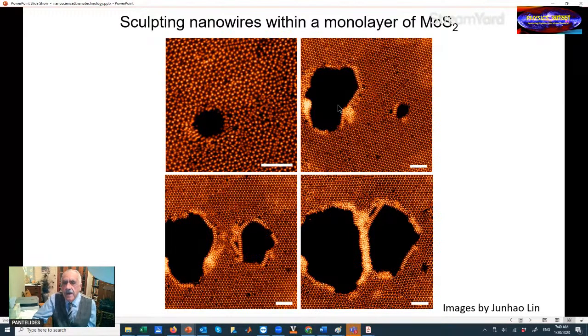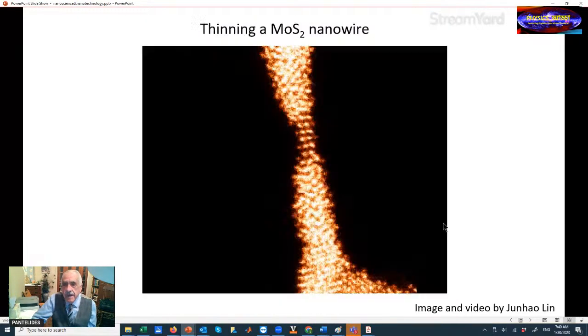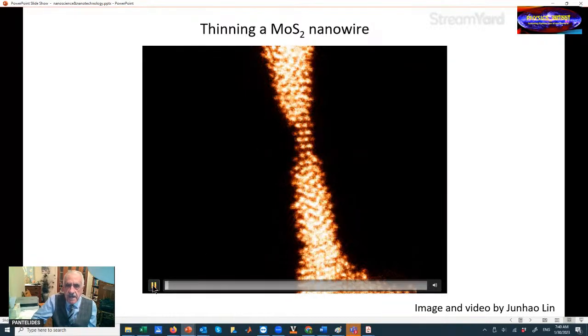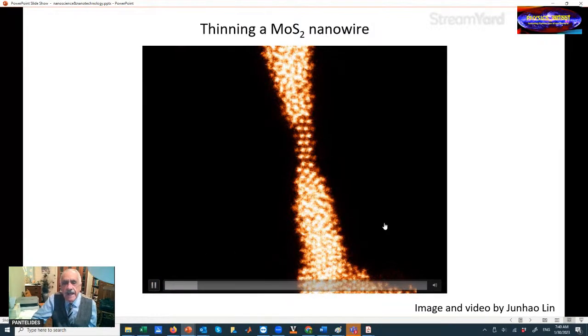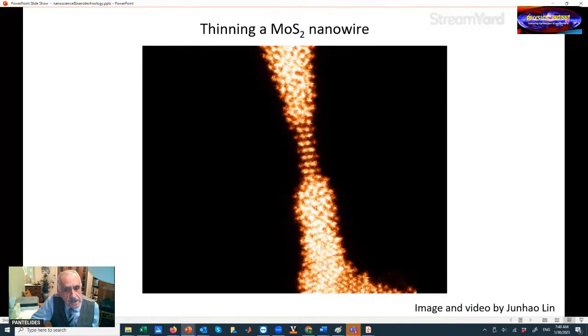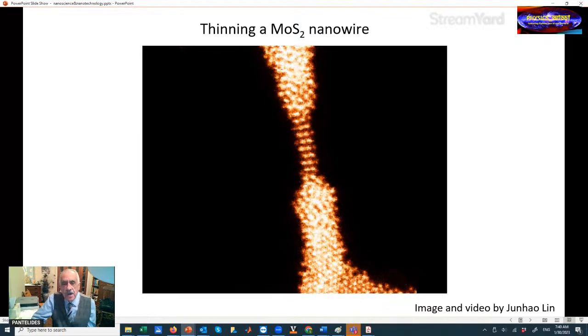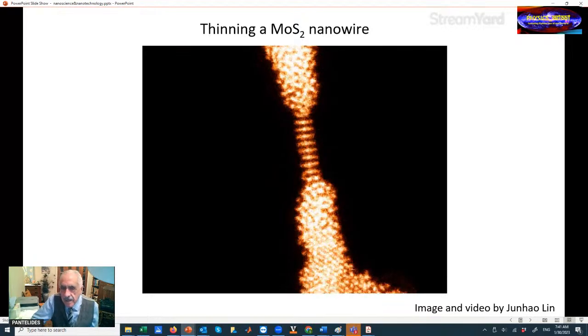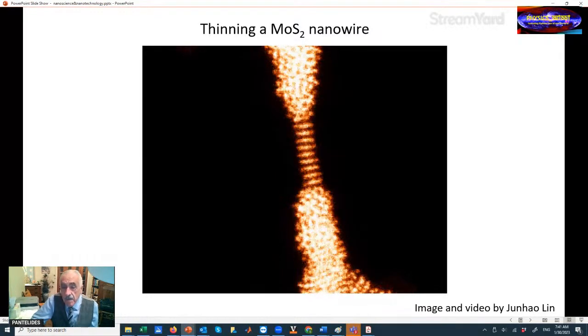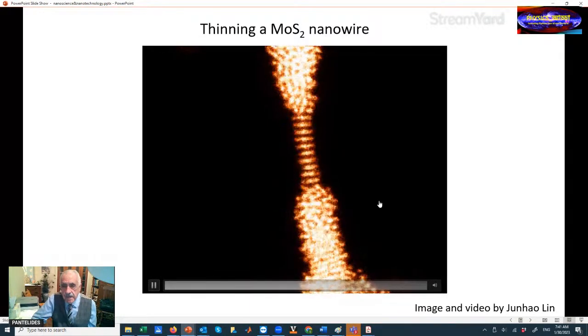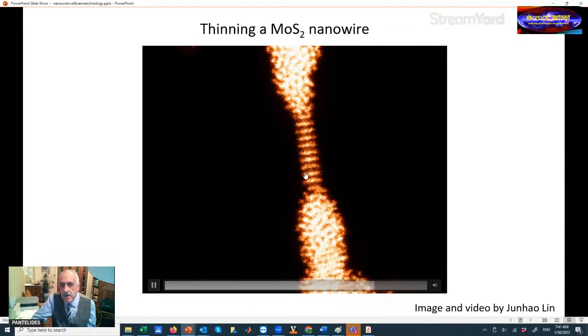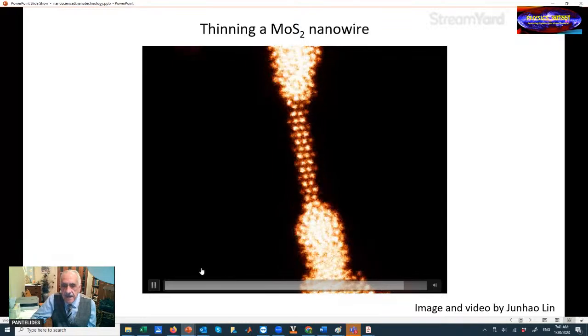You make the hole bigger, then you make another hole, and you make it bigger, and ultimately you end up with what you would call a nanowire. This is pretty fat, but you can thin it down, and you can see it being thinned here by the electron beam while it's being imaged. And all of this, of course, is manipulated by computers. You don't use your hands to do anything. It's all by software, and you guide the software. So you can see how the electron beam makes the nanowire thinner and thinner.